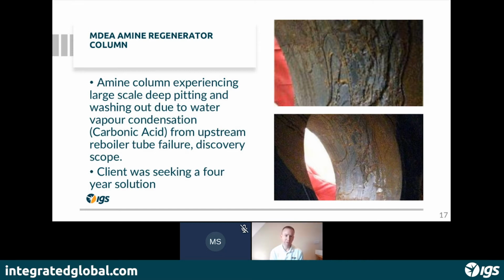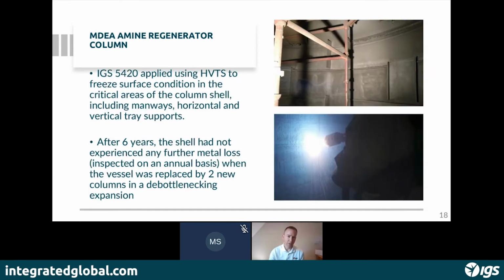The client was looking for initially a 4-year solution. After the application of the thermal spray, they closely monitored the column itself, because these areas where they had low thickness, where they were close to being at their minimum thickness, clearly they had to make sure they didn't lose any more material. Otherwise, they would lose the fitness for service and the license to operate that column. What the thermal spray application allowed them to do was then to plan replacement. So around about 2016, they'd done a debottlenecking exercise previously, and they planned to replace the single column with 2 larger amine columns to improve their process versatility and their flow.